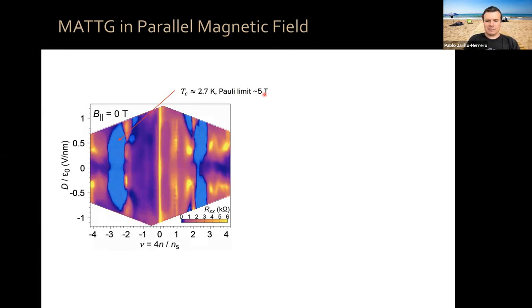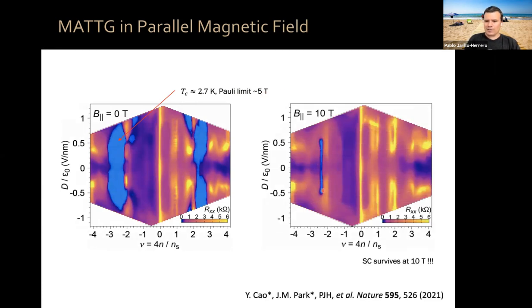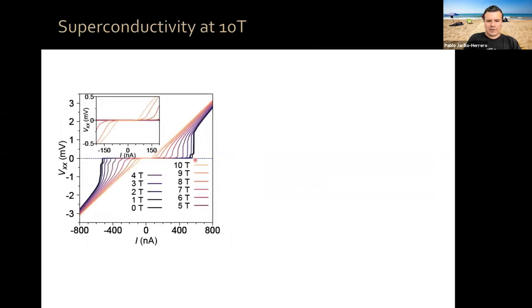Okay, so we measure this exact same data at a parallel magnetic field of 10 Tesla. And to our surprise, we have an extended region where superconductivity survives, at fields well above the Pauli limit. Now we can look at this more carefully. In particular, we can look at the voltage-current characteristics just to make sure that as we increase the magnetic field, we still have a finite zero dissipation region. And we have here this zoom in for 7, 8, 9, 10 Tesla, still flat voltage-current characteristic.